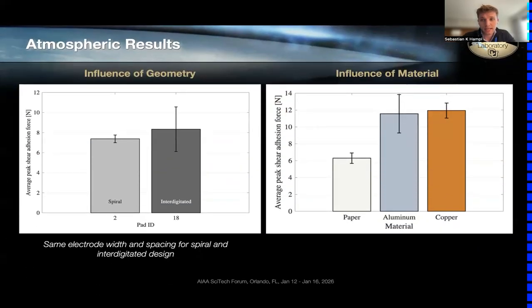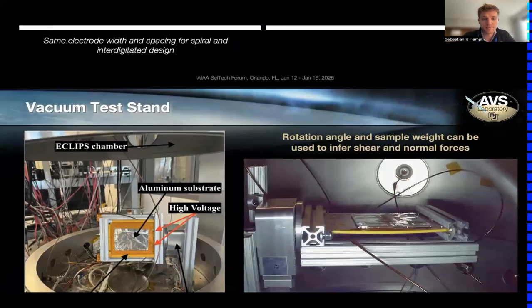Then we also looked at how the geometry influences the results. We tested the spiral design and interdigitated design, and we saw that the interdigitated design performs better than the spiral design, which is not in agreement with previous computational studies, where the spiral was predicted to show slightly higher electroadhesive forces. But again, this is way less pronounced than the effect that a higher voltage has on the achievable electroadhesion force. We also conducted tests on how the pads perform for different substrate materials. And as one can see, it works significantly better on the conductors, aluminum and copper, than on the paper substrate, which is consistent with theory and prior experiments.